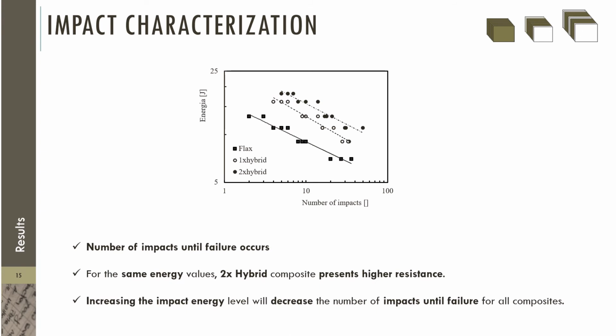In this graphic, we can see the number of impacts until the failure occurs for the different levels of energy. We can see that for the same energy values, the 2x hybrid composite presents higher resistance. We can see here for 11 joules and here for 13 joules. We can also see that if we increase the energy level, we are decreasing the number of impacts, which means that the samples absorb fewer impacts until the failure occurs. This is valid for all composites.